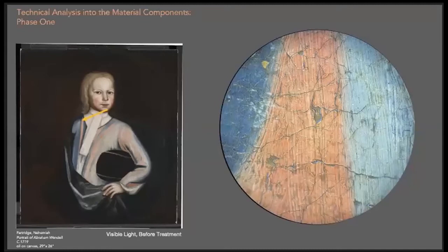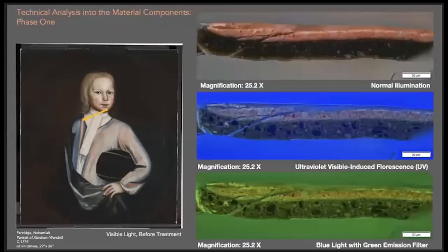Samples were taken in areas of loss, as seen at the right through the ocular of a microscope, in order to better understand the stratigraphy of the paint layers. Those samples were then mounted in an epoxy and polished along the side for cross-section analysis. This is similar to cutting into a cake and looking at all of the layers. To give some perspective as to the scale of the samples, the average human hair is approximately 80 micrometers. Using the 50 micrometer scale in the image as reference, the sample is roughly 400 micrometers, which is approximately the width of 5 human hairs.